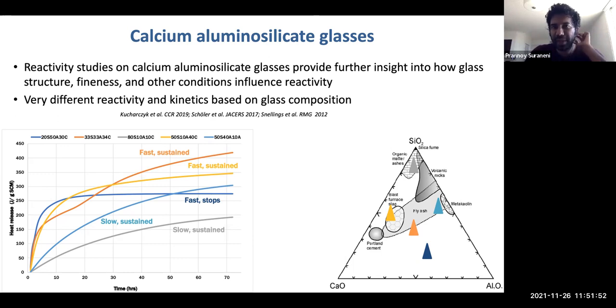So to do that, we have a NSF project which is looking at the dissolution reactivity of calcium aluminosilicate glasses and trying to combine experiments with kinetic Monte Carlo and other modeling approaches. So what we did as a part of this is we generated 8 different calcium aluminosilicate glasses with widely varying composition. We wanted to essentially cover this entire ternary diagram. This just started, so these are very recent results. But basically, we see 5 different glasses here, which show very different overall reactivity, but also incredibly different kinetics, right?